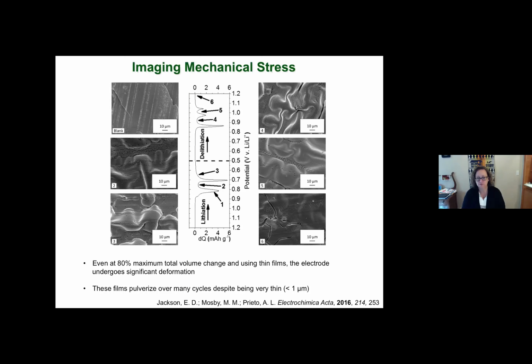One of the advantages of electrodeposition is we make dense films that don't have any binders, and that means that we can study the fundamental properties of these materials without having to worry about the complications of the additives and the binders that are typically used. The trade-off, though, is if you make a high-loading thin film, mechanically it's not stable and it does pulverize. This is a film that was less than a micron in thickness. You see that it does pulverize over many cycles, and that leads to delamination.